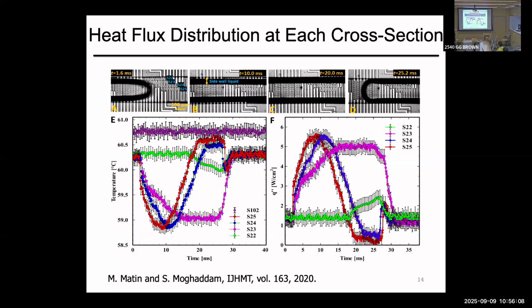So here again, we showed the impact, and then as the bubble moves, at some point the contact line moves back and back, and ultimately even this sensor 22 is impacted at some point, in 20 milliseconds, 15 milliseconds, and you see a little bit of increase and drop in temperature associated. So you could answer a bunch of questions in terms of exactly what happens as you move forward.